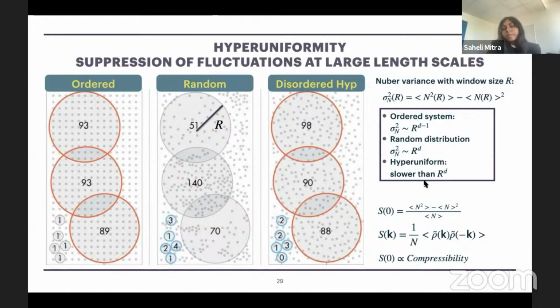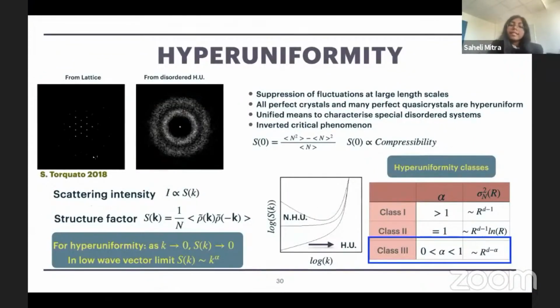Large length scales mean that in the low wave vector regime, we can relate it to the structure factor. The relation of number variance is something like this, and in turn, it is also related to the compressibility of the system. So we can examine a hyperuniform system also from Fourier space analysis, for example, the scattering intensity. Here is an example from a lattice configuration and from a disordered stealthy hyperuniform material, where we see that for the disordered stealthy hyperuniform system, close to the origin, there is no scattering. This scattering intensity is proportional to the structure factor.